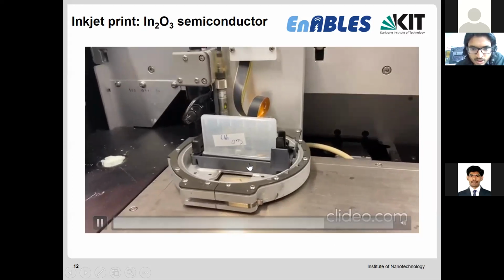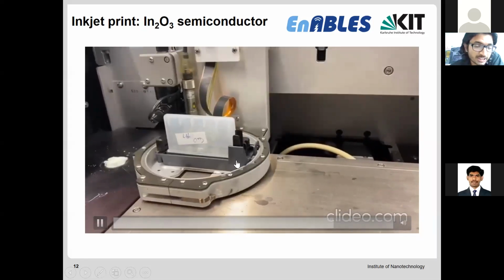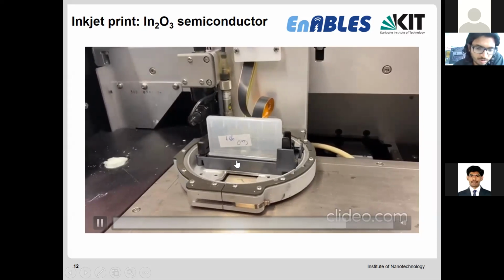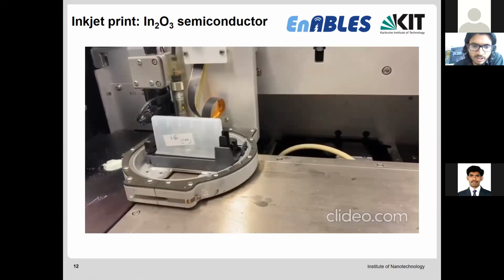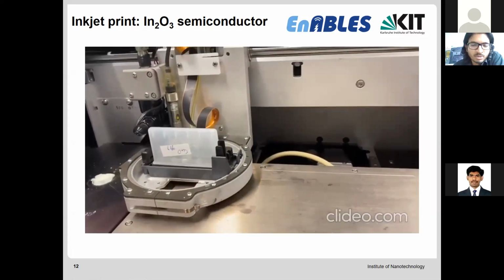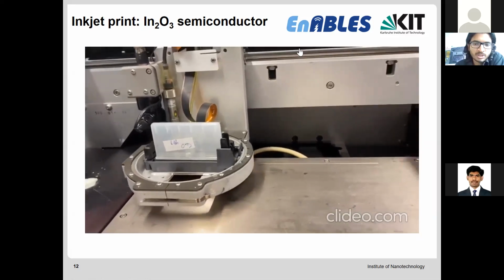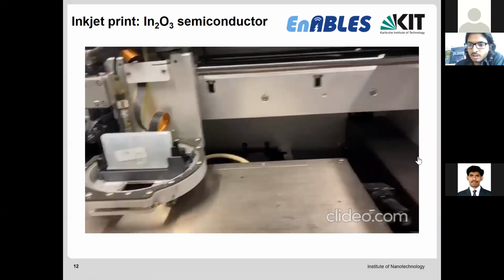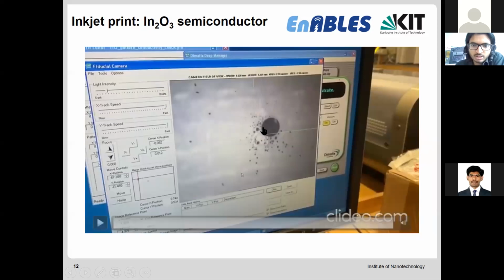The layer thickness also depends on, of course, the substrate, the solvent, and many other factors. For example, here the layer thickness is about 150 nanometers, and here we wanted to print a circle, and you can see quite a good circular shape. And these, as I told you before, are some satellite drops which arise because of the imperfect viscosities of the ink.